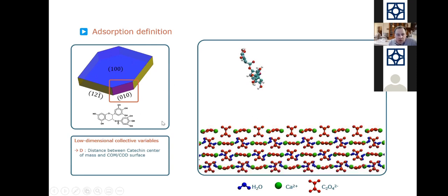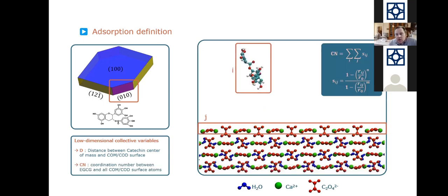So first we need to define some variables in order to follow what's going on. In order to study the adsorption, we need to have a first logical parameter, which is the distance between the molecule and the surface. The second one is what we call the coordination number, defined here. I don't go into details, but in fact, it counts the number of neighbors. Especially when you're close to the surface, you will have a high coordination number. So a strong adsorption will be translated by a low D and a high Cn. A short distance and a high coordination. This is what we will follow.